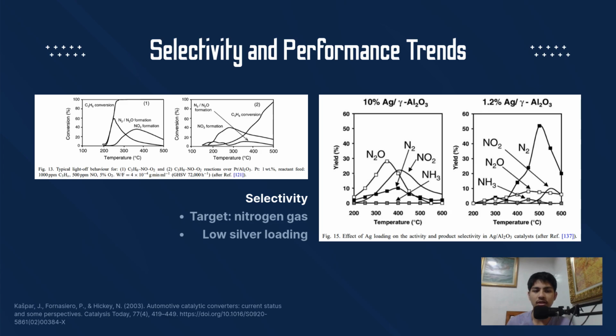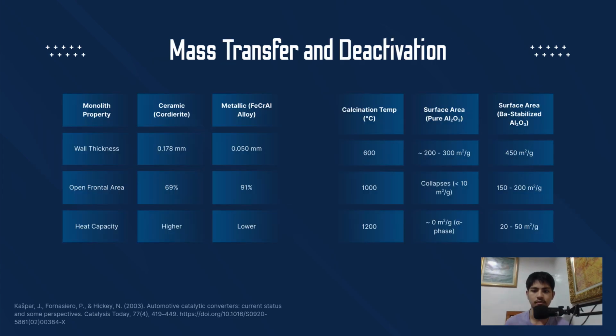In Figure 13, we see that performance is highly sensitive to the fuel type. An alkene, like propene, allows the catalyst to reach high efficiency very early, whereas an alkane, like propane, fails to exceed even 10%. Furthermore, Figure 15 shows that while 10% silver loading results in poor selectivity, reducing that loading to just 1.2% achieves excellent nitrogen gas production at high temperatures.